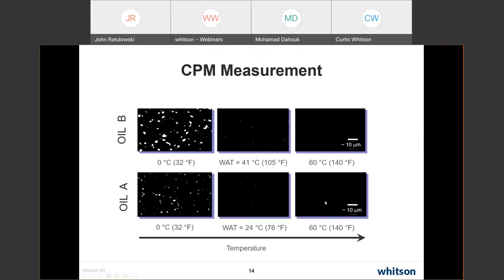You can see here at high temperatures, there's no little white dots, so there's no wax there. As you come down, you get these small white dots, and you can see them here. These are actually pretty good pictures, and it's pretty apparent that you're down below the wax appearance temperature. But when these things first start coming out, they're really small and very difficult to see.